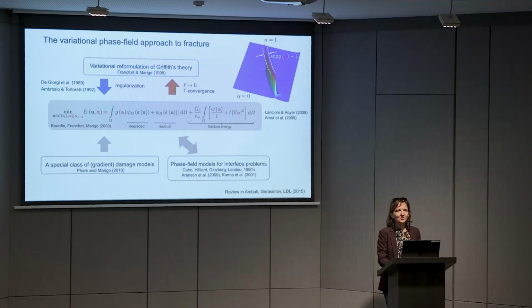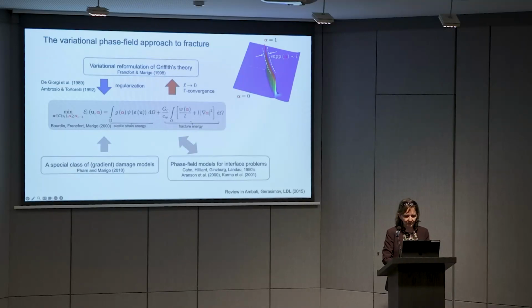Okay, this looks almost too good to be true. In fact, it is too good to be true because this functional has a lot of issues still. First and foremost, the issue is that the functional, as you see it here, doesn't see whether you have tension or compression, right? So the elastic strain energy density is still positive in both cases. So if you had compression, you would still get a fracture under the same loads that you would get under tension. And we all know this is totally unrealistic. And this also cannot incorporate the unilateral contact constraint among faces of a developed crack as you try to push them together.